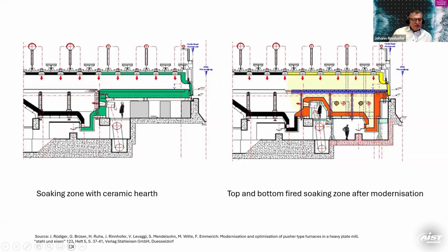So what we did in the end, just to preempt it, we took out this soaking hearth. We dragged it down completely in a few weeks and rebuilt it with an actively heated soaking zone. That is shown here on the right side. So now we can have burners here. We can have an actively heated area in the bottom of the furnace here. And obviously the upper part was left as it was originally. And so that gave us the option to completely change the heating strategy.